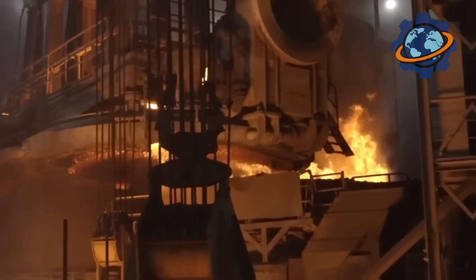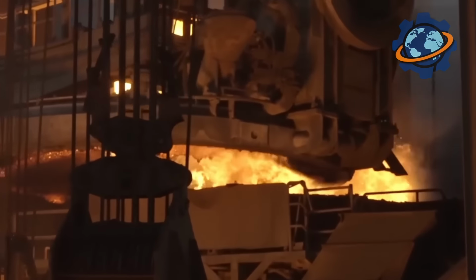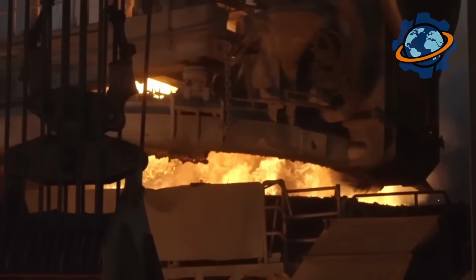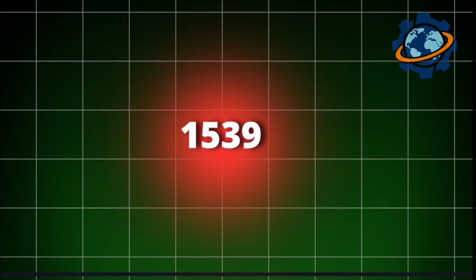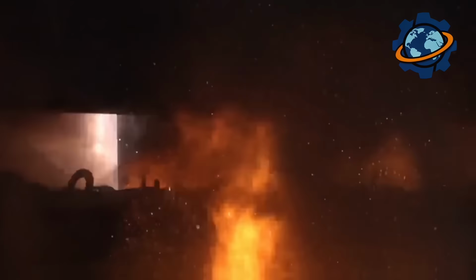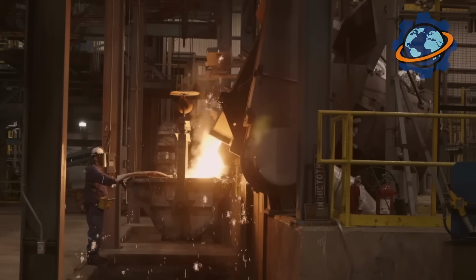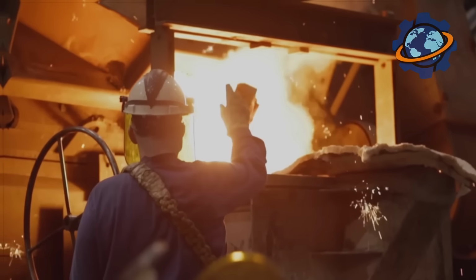And here's where something amazing happens. Pure iron melts at a very high temperature of 2,800 degrees, 1,539 Celsius. But soaking up carbon dramatically lowers that melting point. That's why a blast furnace doesn't produce pure iron, but an alloy of iron and carbon, pig iron, which becomes liquid at just 2,200 degrees, 1,200 Celsius.